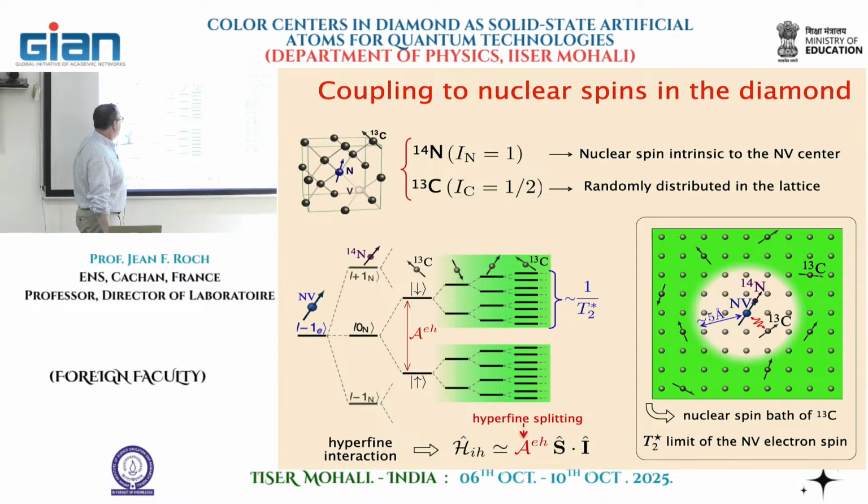And then we have now 2 peaks that appear, associated to the 2 quantum states of the carbon nuclei, and separated by the hyperfine interaction associated to the coupling with the NV center. Okay? And you can continue with that. So there's really a big manifold. You can now have another interaction with another carbon atom, like this one, for instance, and that will again produce new 2 states, et cetera, et cetera.